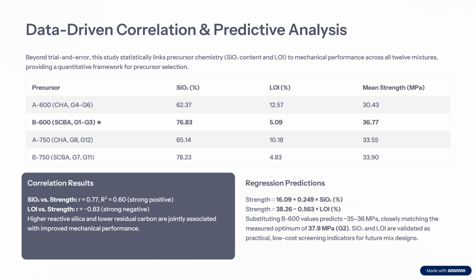For the correlation, we can say SiO2 versus strength has an R squared of 0.6, a strong positive, and for the LOI the R is around 0.83, a strong negative. So higher reactive silica and lower residual carbon are jointly associated with improved mechanical performance.